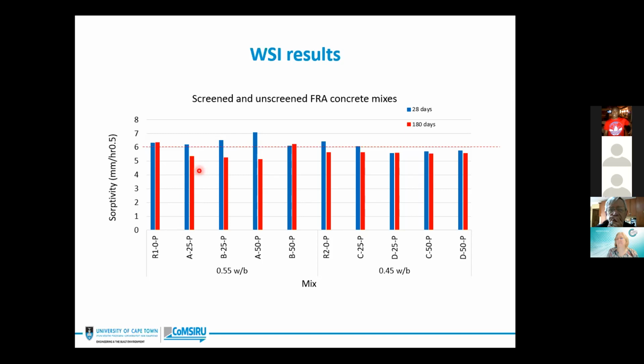As we can see, there is a decline in the sorptivity values from 28 days to 180 days of curing. This can be attributed to a better microstructural development over a longer curing period.